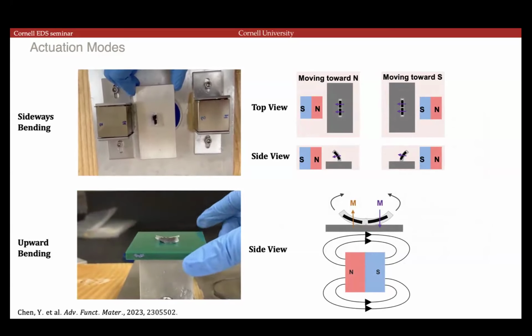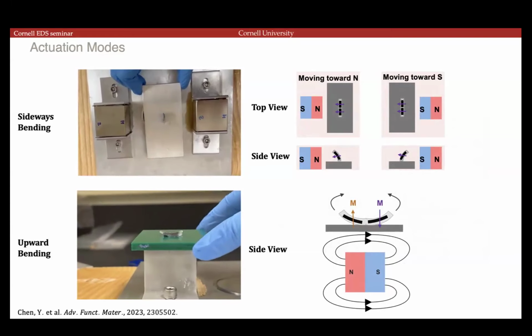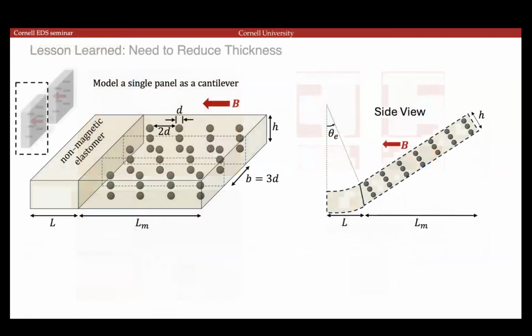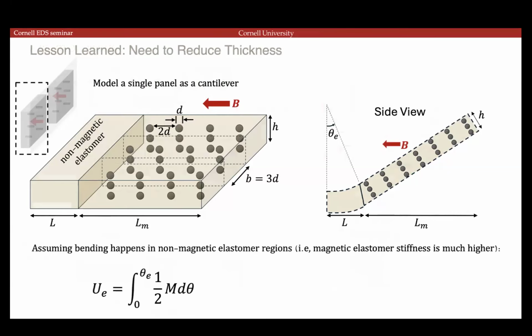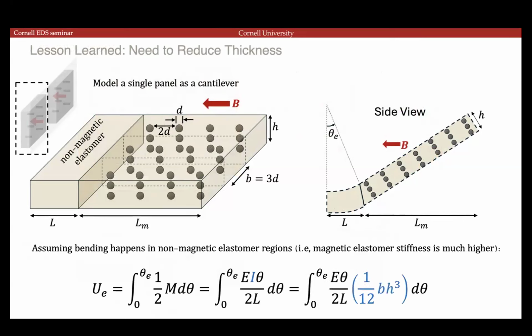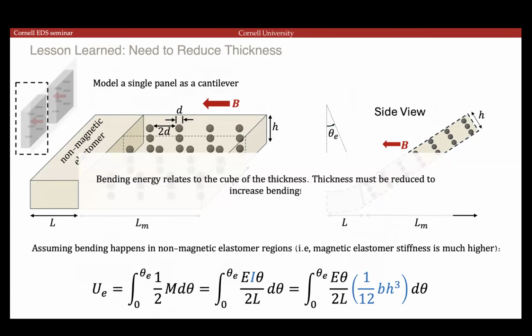But it's still quite thick and it's not integrated in an actuator. Without going too much into detail of the theory, we can consider how to make this even better. The main thing is that if you look at the elastic energy, the biggest contributor is how thick your material is. The moment of inertia is related to the thickness. If we reduce the thickness, we'll get a significantly larger amount of deflection.